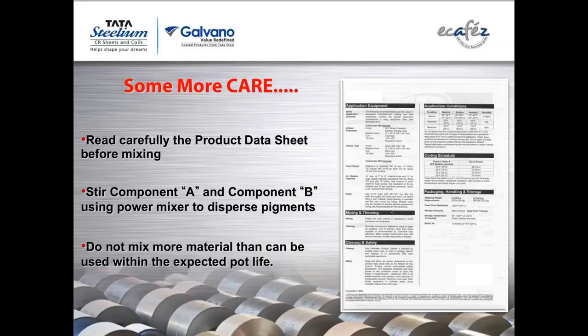So try to follow everything they are mentioning. Second thing is stirring of component A and component B again with a power mixer before you mix them, because there are pigments in that which will settle. All these pigments we talked about earlier, like zinc we are mixing externally, but zinc, phosphate and other pigments are heavier, so they have a tendency to settle down. If you do not disperse them again, those pigments are not going to work and naturally you will not get the full potential benefit. And again, what we discussed in the earlier slide: do not mix more material than can be used within the expected pot life. If you take these things into consideration, I think there should not be any problem using these paints.